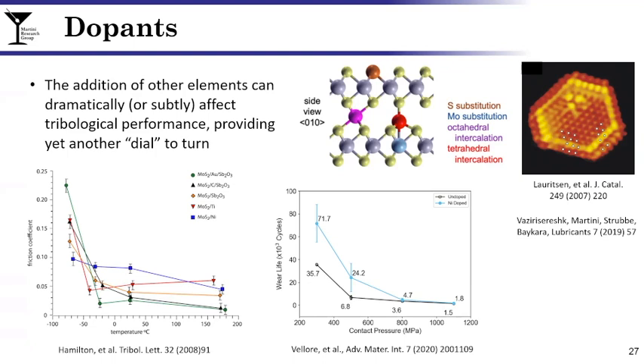On the left image, you're looking at friction as a function of temperature, with MoS2 having various dopants. And quite interestingly, this shows that if you're looking for high temperature behavior, perhaps you're looking at a gold dopant, or the green line here perhaps. But if you're looking at cold temperature behavior, again, back to the example for space applications, then you might be looking for a nickel dopant. So with very small concentrations of elements, we're completely changing the profile.